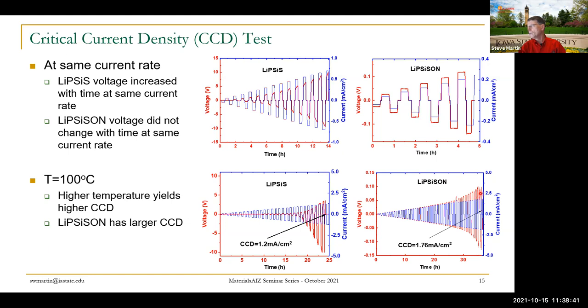And finally, when we get up into this range far above the 1 milliamp we need for our cell phones and automobiles, we push it too hard. Eventually, you can't see it very well, it shorts out here. That's our critical current density. At about 2 milliamps, we reach our critical current density. But 1 milliamp is sufficient, so we could get good behavior out of this oxysulfide nitride glass.